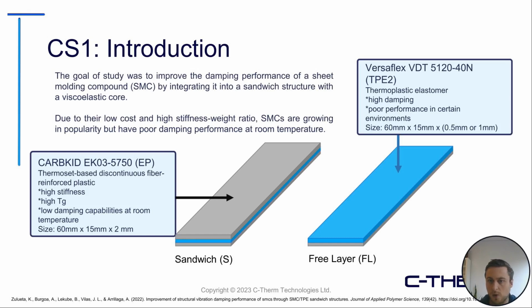And the viscoelastic core was a VersaFlex thermoplastic elastomer, which they labeled TPE2. The 2 comes from staying consistent with previous reports that they worked on with these sandwich structures. This thermoplastic elastomer has high damping, but poor performance in certain environments, especially when it is exposed to oxygen.